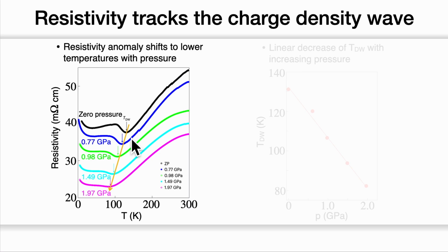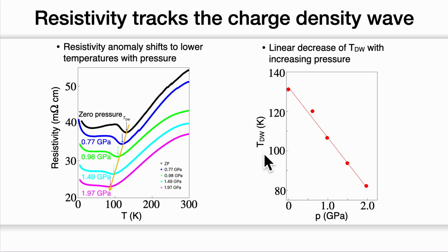As pressure increases, this shifts to lower temperatures, indicating that the transition temperature of a charge density wave decreases linearly with pressure. And this also implies that the charge density wave becomes unstable as we increase pressure.